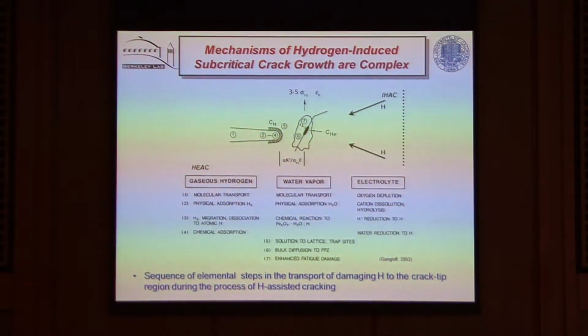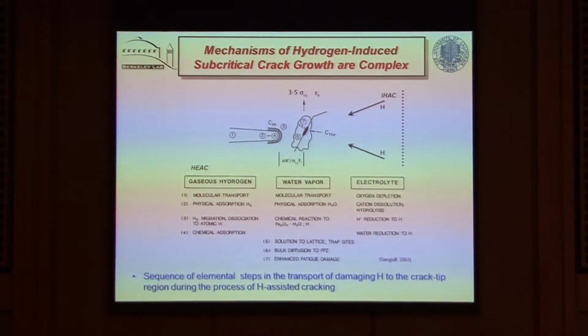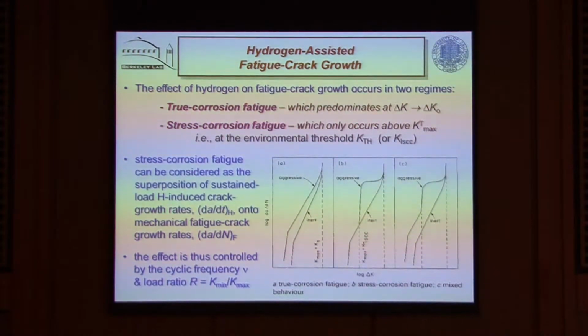Now, mechanistically, there are a whole plethora of mechanisms that are important. There are transport mechanisms of how hydrogen gets to the crack tip. There is oxide at the crack that has to be penetrated. There is the mechanics of how the hydrogen affects the fracture inside the material, be it some decohesion at an interface or a dislocation pile up against an interface. And it needn't be gaseous hydrogen, we can generate hydrogen in an electrolyte just from the oxidation in water, for example. All these mechanisms are extremely complicated, and they still need considerable work to be done on the scientific basis. But in terms of the engineering side, these are embedded into crack tips, and we can see certain patterns. As I said, we talk about what we call true corrosion fatigue, where the effect of hydrogen is occurring primarily at lower stress intensities. And people talk about stress corrosion fatigue, where we get this sudden superposition, this sudden elevation of the crack growth rates in hydrogen. And of course, in most cases, we have both these phenomena.